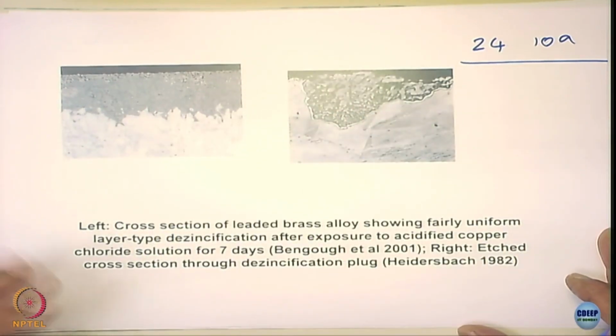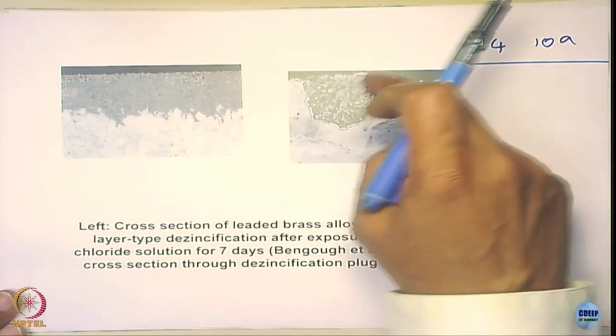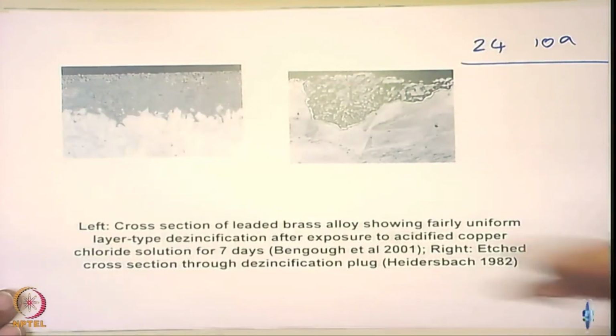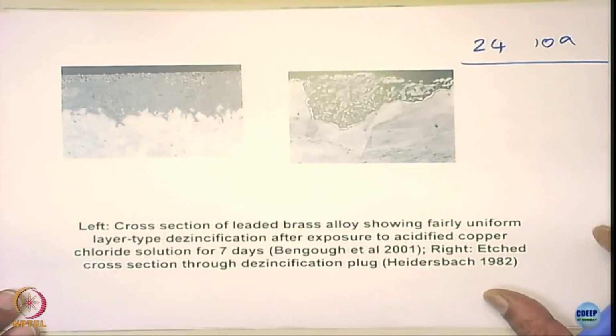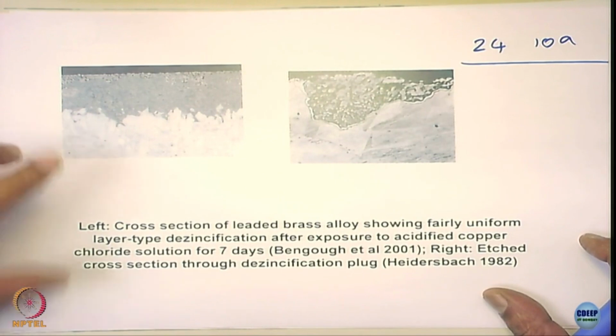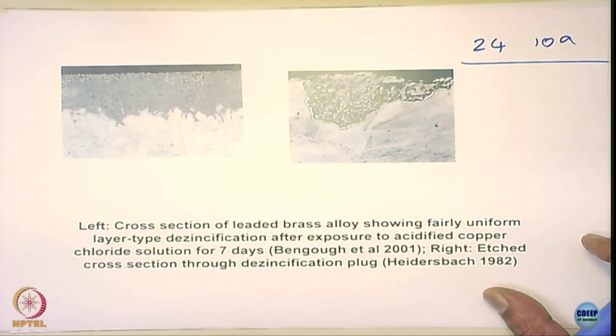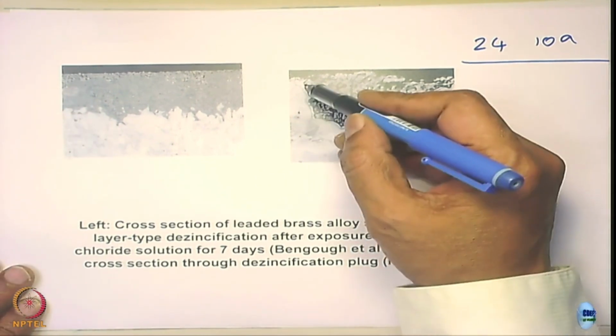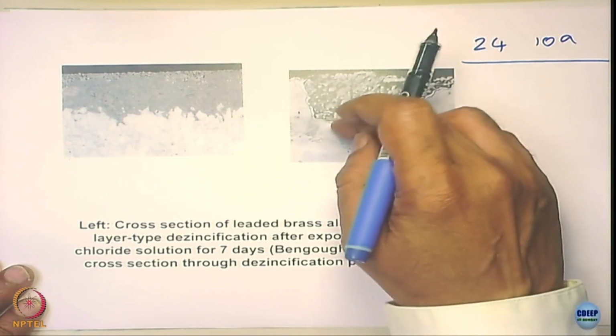It depends upon the alloy, and it depends upon the environment. You can have a plug type, this is called a plug type, and this is called a layer type. Now please notice, if I remove zinc from brass, what will happen to strength? It reduces, because zinc is what is giving the strength. And in this case it not only reduces strength, it also brings stress concentration at this kind of pits. So this is the other kind of problem.